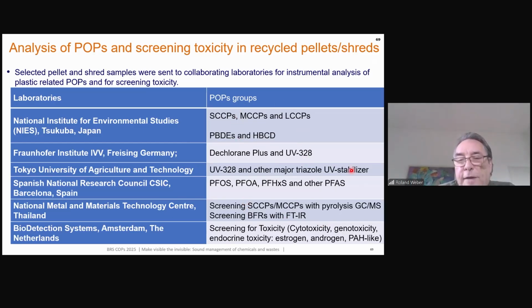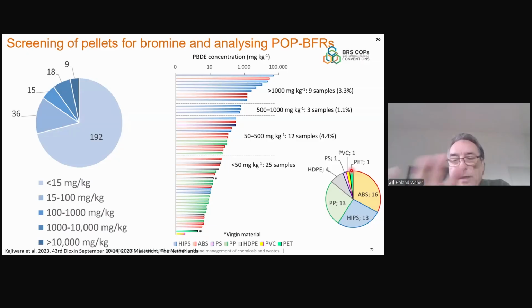And the different institutes have screened for different POPs. I just show you very few results in a minute. One is on PBDEs. These were found overall in the highest concentration. And you see from these recyclates, we first screened with bromine. You see here from the 270 pellets, 190 pellets were below 15 milligram per kilogram. And this shows nearly 3/4 of all samples didn't contain any brominated flame retardants. And this you do not need to analyze. And the others we analyzed.